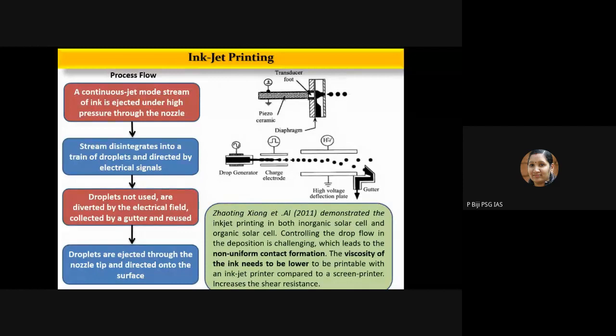In 2011, Xiong et al. demonstrated an inkjet printed silicon solar cell and an organic solar cell also. Controlling the drop flow in the deposition is very challenging in this particular process. This may lead to non-uniformity in the contact formation. Also, the viscosity of the ink should be lower to be printable with the inkjet printer compared to the screen printer. That will actually increase the shear resistance.